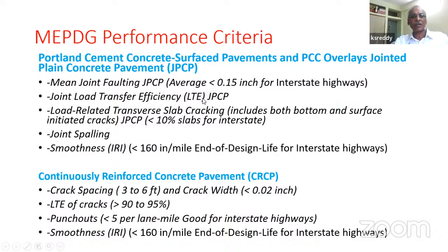The load transfer efficiency, theoretically there is no criteria, but we expect a certain level of load transfer efficiency. Let me skip this. The amount of transverse cracking, the percentage of slabs having certain degree of transverse cracking should not be in excess of 10%. This is a performance indication in terms of physical problems that you see there. There is a performance indicator in terms of joint spalling. There is also an indicator in terms of roughness. If you can estimate all these, they go as an input parameter for estimation of roughness. So you can control the roughness directly in terms of these parameters.